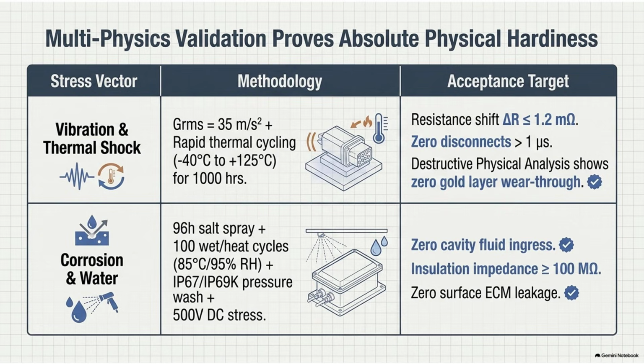First up, vibration and thermal hell. The testing standards dictated here are frankly abusive. They take the entire heavy power control system and bolt it rigidly onto a massive 3-axis electrodynamic shaker table. And they program that table to violently shake the system with a random chaotic force of 35 meters per second squared RMS. That is almost 4 times the force of gravity, thrashing in every direction simultaneously. Continuously, without stopping. For 1,000 hours, that is over 40 solid days of relentless high-G mechanical assault.